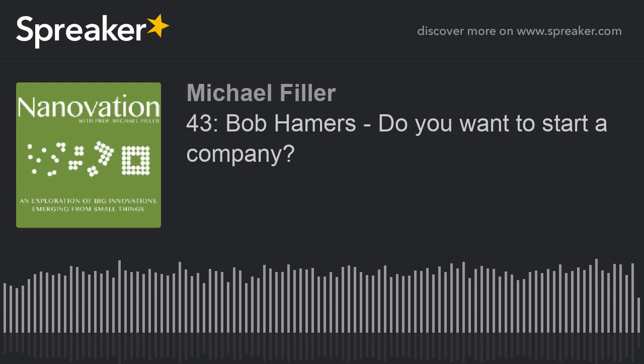Yeah. So what we typically will do is take these materials, and we can synthesize them in these sheet-like forms. A sheet almost looks like cornflakes. That's the way I describe them. They're little nanoparticles that are maybe 120 nanometers in diameter. So that's about 100th the width of a human hair. Usually a human hair is about 10 microns, or 10,000 nanometers. So these are maybe 100th that size in the long dimension. And in the thin dimension, there may be only 5 nanometers.